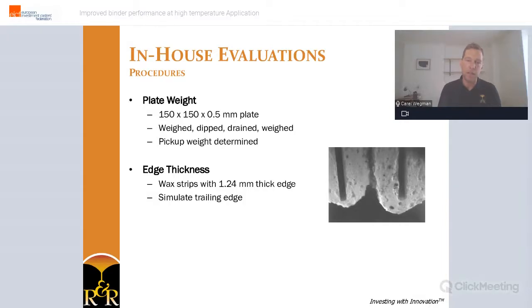The edge thickness test is intended to show how the shell is building up around a very thin edge. Thin wax plates were used for this purpose. The thickness is representative of the thickness at the trailing edge of a gas turbine blade. The strips were shelled according to the general shell sequence, and after the samples were cut, fired to burn off the wax, and visually examined to reveal the thickness variations of the flat side and around the edge.